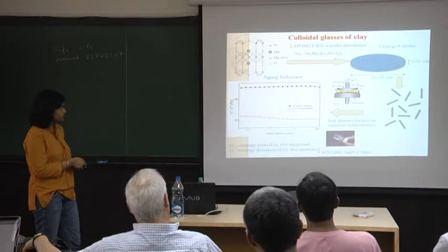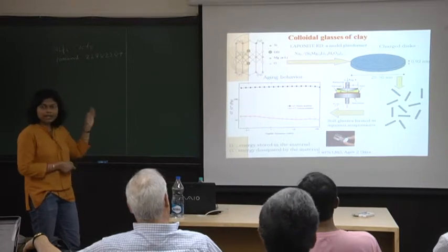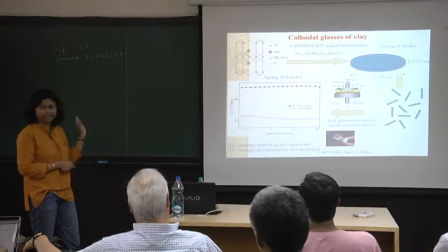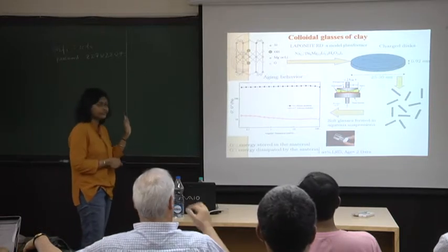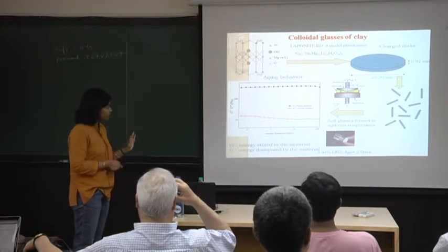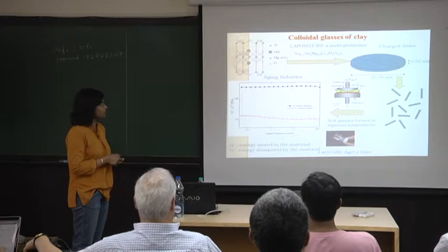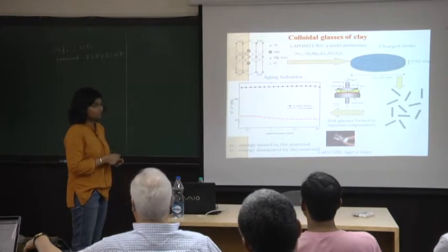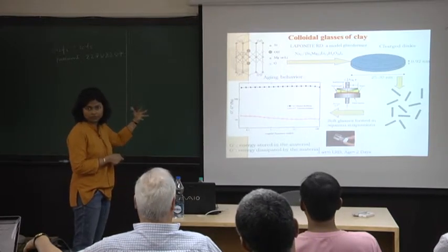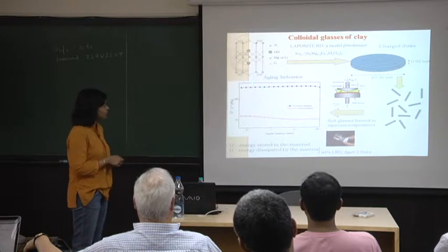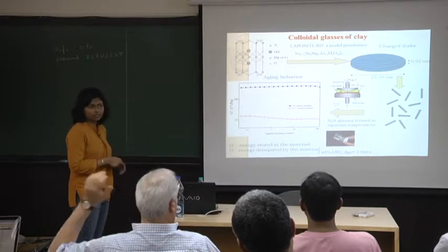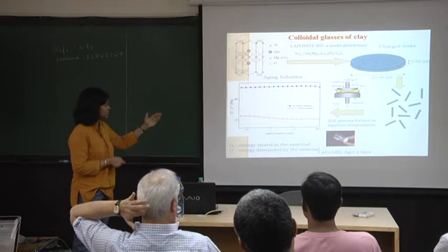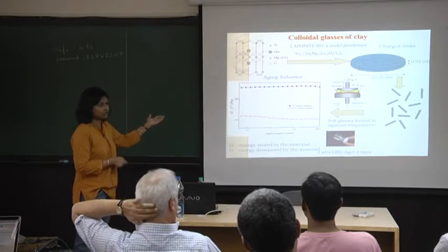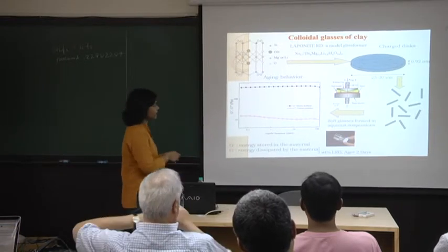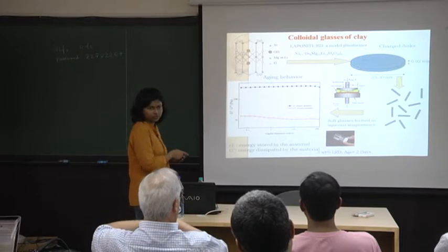So this is a frequency response measurement. This is data of elastic and viscous moduli taken at a certain very low strain, but over a range of frequencies, and you can see here that the solid-like contribution to the mechanical modulus is far, far larger than the liquid-like contribution. This is when the system is, I think, about maybe a few hours old. Okay, so you can actually see the relative proportions of these two changing.